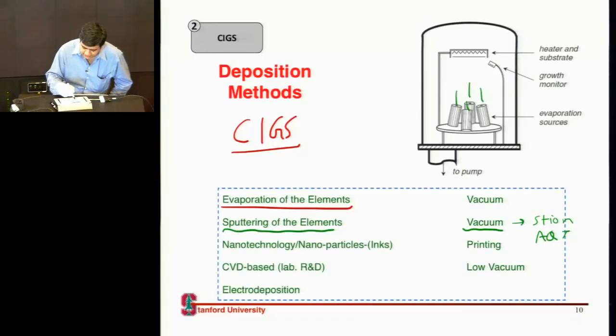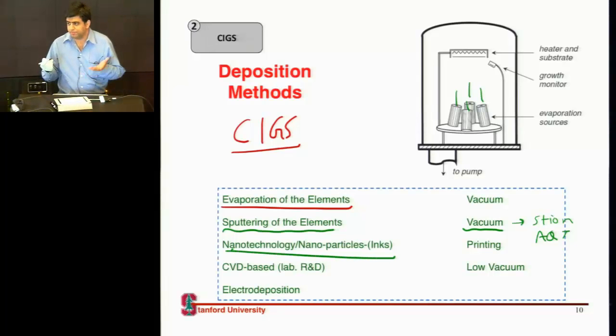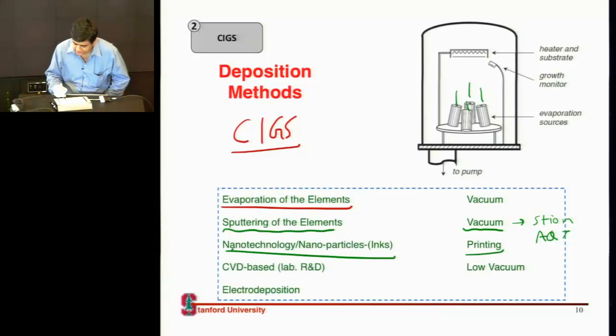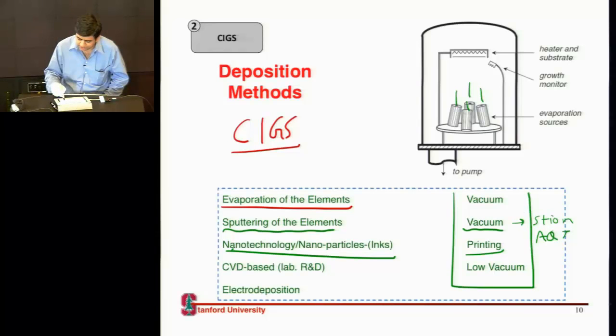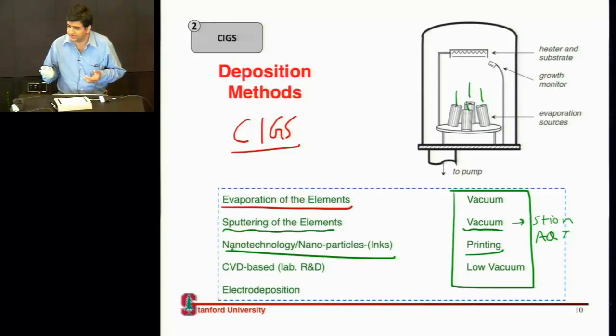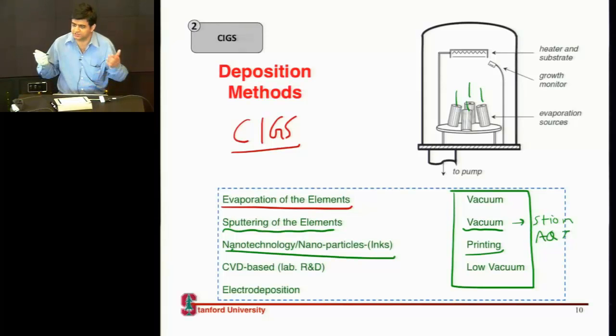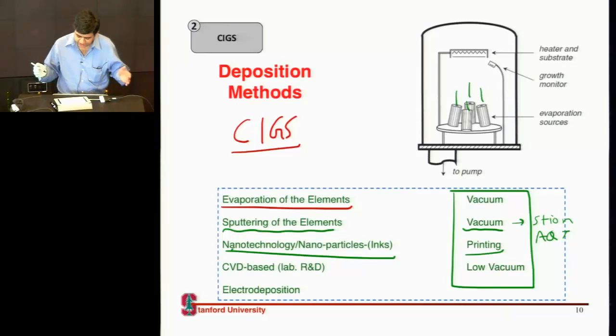The other way is to print them — essentially deposit or print the CIGS material in the form of an ink. In the video I showed you last time from Nanosolar, they exactly do this: they take an ink of CIGS and print it over, then anneal it to hopefully give good quality material. When comparing methods, you should take into account what vacuum you are operating at. At high vacuum you'll be slow, but you won't have contaminants like oxygen or carbon incorporated into your film. Under atmospheric pressure you'll get a lot of oxygen and carbon, which are bad for the cell. So each of these startups is essentially a tool and process startup that develops a proprietary process to deposit this CIGS layer.